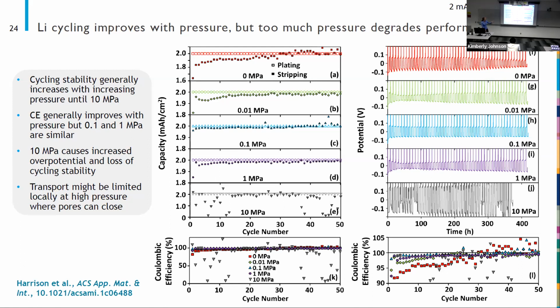And I'll talk a bit about overpotential, so I want to explain what that is. In equilibrium conditions at very slow kinetics, we would expect the lithium to plate and strip at zero volts. But if we have kinetic limitations in our system, then we have to apply more voltage to get these reactions to go. And so the size of that increase in voltage is what we call the overpotential. And there are various sources that cause the losses that lead to that overpotential. These are all galvanostatic experiments, which means that they're constant current and we're measuring the voltage. So if we're putting in a constant current, the voltage has to adjust itself in order to be able to run the electrochemistry.